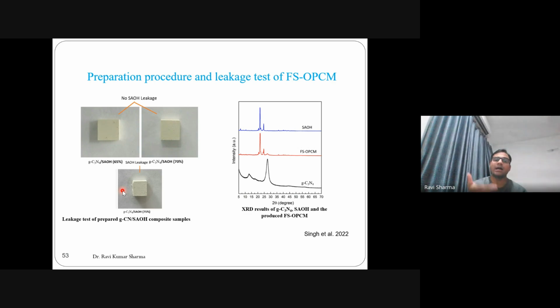The temperature was higher than the melting point of the PCM. What you see on screen is some impression around it, that's nothing but the molten PCM. When 65% and 70% PCM were added, there was no leakage at the same temperature, but when the amount of PCM increased to 75%, there was leakage. So this composite is optimum for thermal energy storage purposes. At the same temperature, the pure PCM melted, but this composite did not melt, meaning form stabilization or shape stabilization has been achieved because the PCM is not melting at this point.